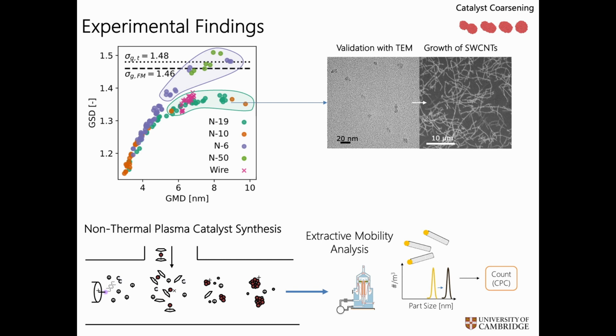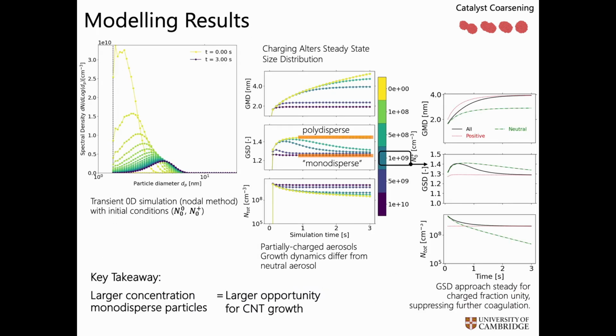And so if one brings charges into a system, i.e. plasmas often have lots of charges around, and if we can control those charges to predominantly one polarity of those charges to attach to particles, you can get dramatically lower geometric standard deviation. So this is what nature is bringing you to, and this is where we've been able to get some work recently and then grow nanotubes from these materials. It gets very mathy, but let's just say that one can produce relatively monodisperse particles when you introduce charge into the process, and we can do that experimentally as well as in our equations and ultimately describe that.